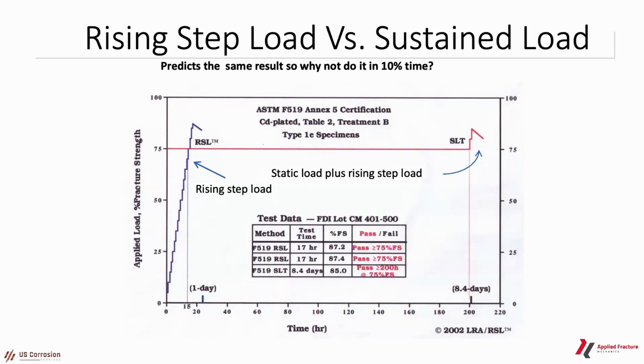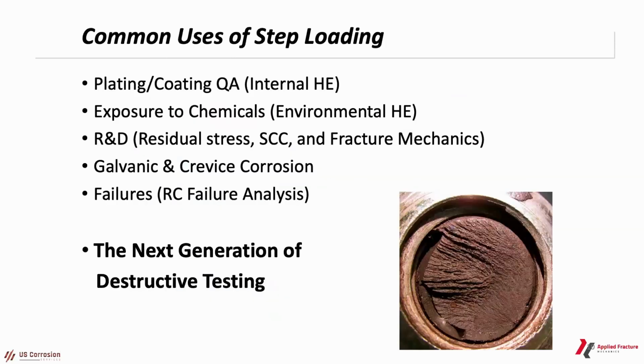But once you include machining, setup, takedown, data analysis, typically you're looking at 2 to 3 weeks to get your test results. And in comparison with the step loading, we can get the same results in 1 day. For softer alloys, this might be 2 days or 4 days, but still it's a pretty quick test. And the other thing is it's quantitative. So wherever you end up finding the threshold, that's an actual number instead of just a pass-fail at 75%.